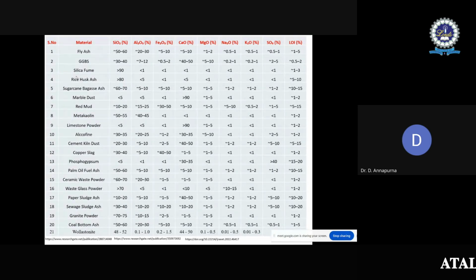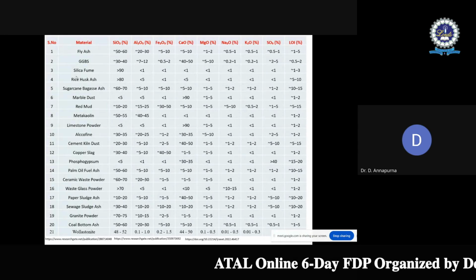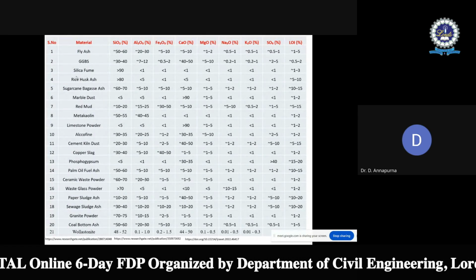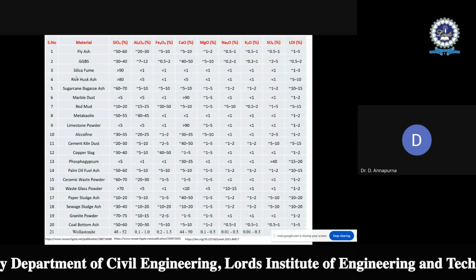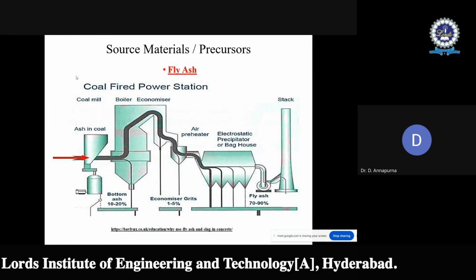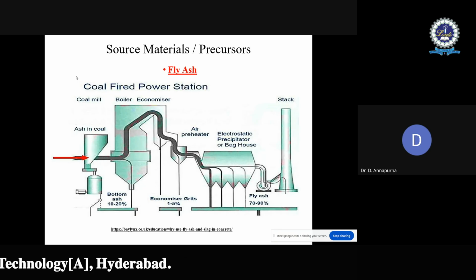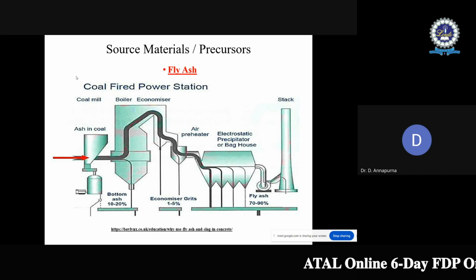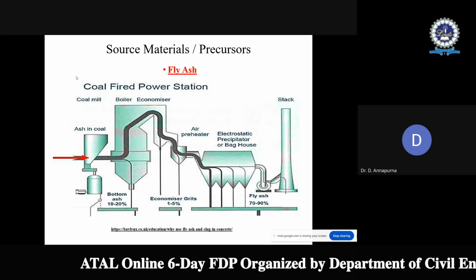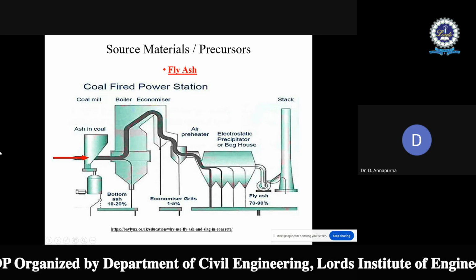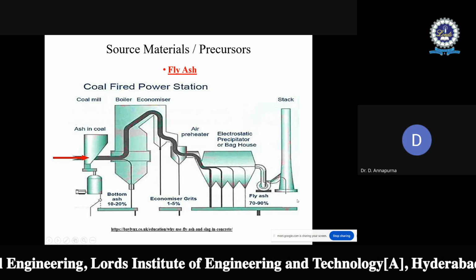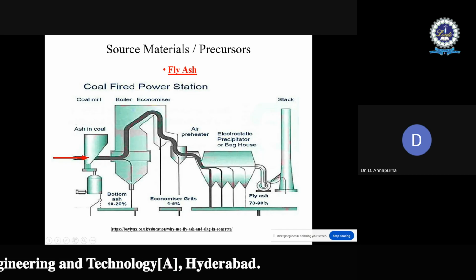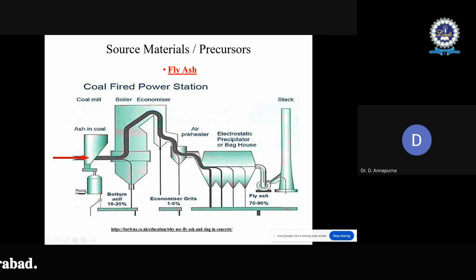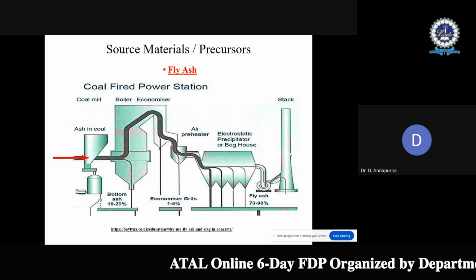So after looking at the geopolymerization process or chemistry of geopolymer concrete and the source materials, now we'll switch to how the source materials are produced. What is the source? Fly ash is produced from the combustion of coal in thermal power stations. From the thermal power stations, we get two kinds of ash: one is bottom ash, the other is fly ash. Bottom ash is coarser in size than fly ash and its reactivity will be less than fly ash. Fly ash is the one captured from the flue gases using an electrostatic precipitator.